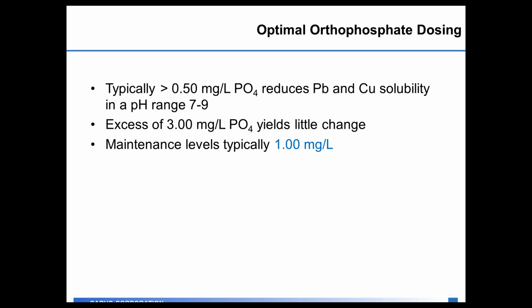When we talk about an optimal orthophosphate dose, typically you're going to be at a minimum of 0.5 milligram per liter as orthophosphate. And that's going to help you reduce lead and copper solubility in the pH range of 7 to 9. The US EPA documents talk about feeding up to 3 milligrams per liter as orthophosphate in the distribution system, and that as you increase that dosage from 0.5 part to 3, you'll continue to see reductions in lead and copper solubility out in the distribution system.